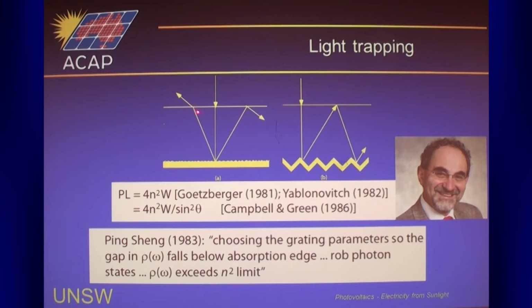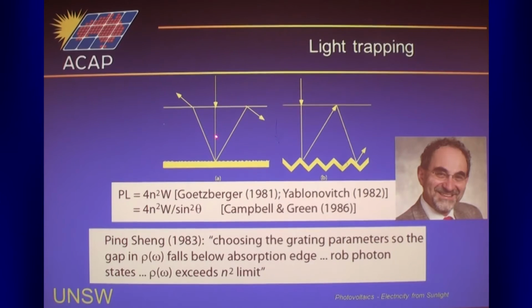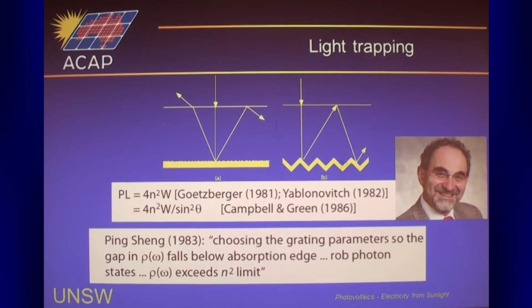And if it's reflected within the escape cone of the silicon, it'll go straight back out. So the escape cone of silicon lies within about 16 degrees of the surface, in a range of about, I think it's 8 degrees half angle. So if it's reflected within that half angle, at this angle here, is small enough, it'll just go out of the device, getting refracted this way when it hits the air interface. However, if it's reflected at a little more oblique angle, it gets totally internally reflected at the surface. And total internal reflection is like 100% efficient process, unless you have dust or something on the surface of the device that can help couple the light out. But if you had nice pristine surfaces, total internal reflection is effectively a 100% reflector. So you can't do too much better than that.